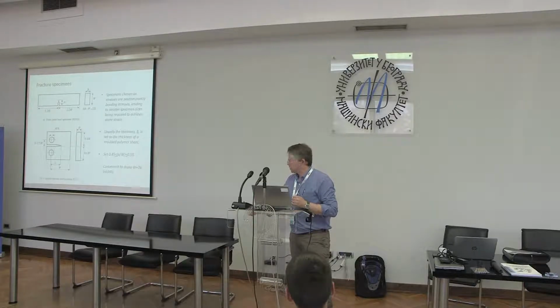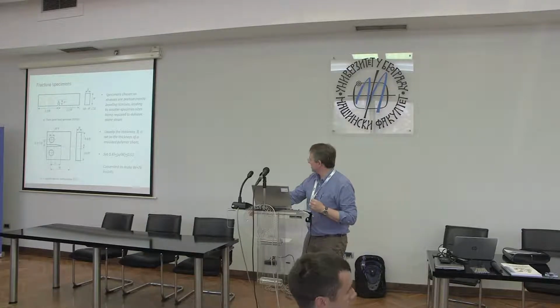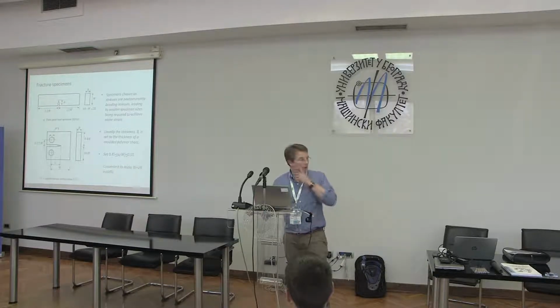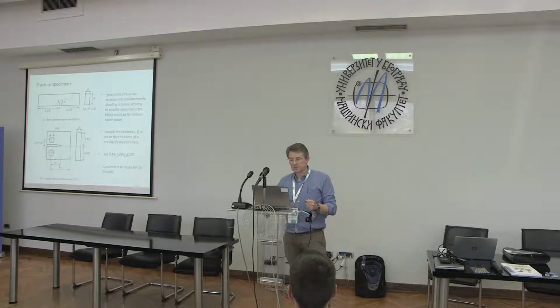So we have reasonably compact specimens. Of course, for a polymer, we're usually moulding sheets of material, so these might be injection moulded or they might be extruded and cast. But normally we'd set the thickness of the plate to be the thickness B of our specimen. And then we'd machine those specimens out. So we'd set an initial crack length. So if we normalise that crack length with the width of the specimen, a upon W, we're looking for an a upon W ratio of about 0.45 to 0.55 to start our specimen off. And we start off making the specimen with typically a width W of about 2 times the thickness, and we can move from there. So that's usually the starting point.